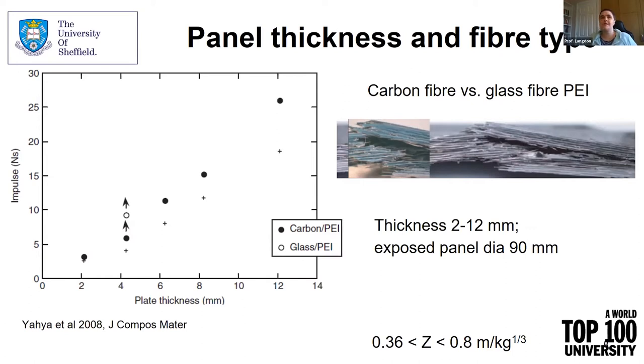The graph shows the impulse required to cause different levels of failure in the composites. The crosses indicate the first impulse at which fiber damage was observed. So you can see the crosses here. Hopefully you can see my arrow pointing at them. And you can see that they increase almost linearly with different laminate thicknesses. The circles indicate complete failure of the laminate. And if there's an arrow on the screen, it indicates that we weren't able to get complete failure in the tests that we performed, so you're showing the highest impulses there and showing that there is still some more failure capacity in them. That also increases roughly linearly. The interesting one there is that you've got a comparison between glass and carbon at just over 4 millimeters plate thickness.